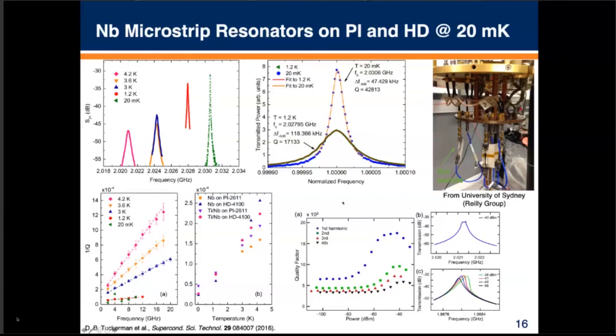We did see some interesting responses here as a function of power for these resonators. And you can see the different harmonics of this resonator. And as you continued to drop down in power, you could see the Q reduce a little bit. That's evidence of extra loss at low powers or low photon count. And it's not unlike what you would see with two-level systems in quantum systems. So there are some interesting things buried in these structures if you really wanted to start looking at them from a quantum perspective.